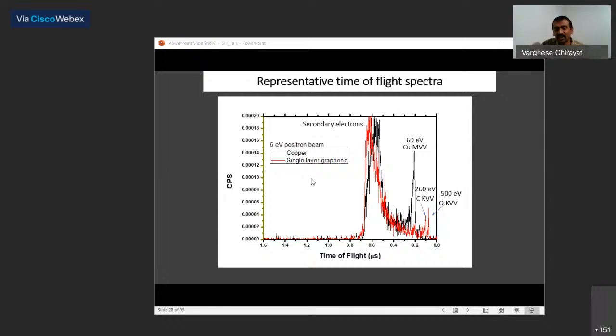And then we took the spectra again, and you clearly see differences here, right? Let me point out the peaks over at the left region here. Before cleaning, the main peaks that you see are carbon KVV. I hope you know what KVV means. And you have the oxygen KVV peak. After removal, you don't have any carbon and oxygen anymore, and you have the copper MVV peak. So now you know that you're looking at copper.